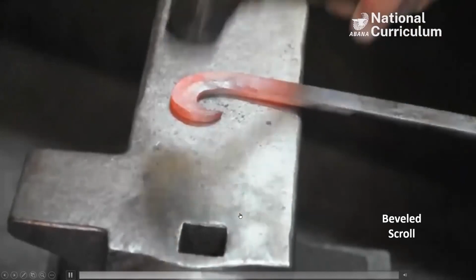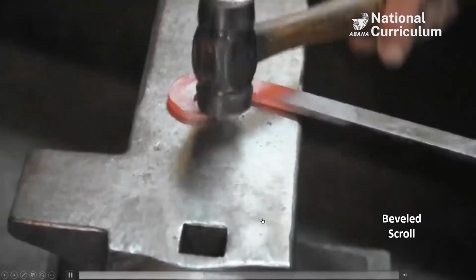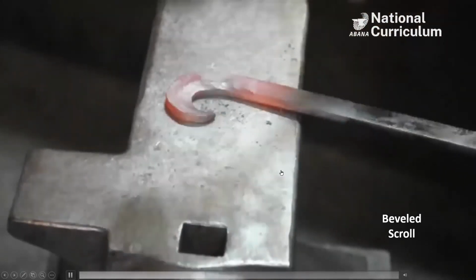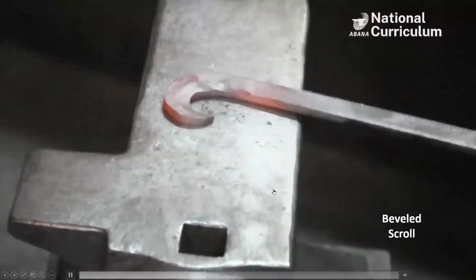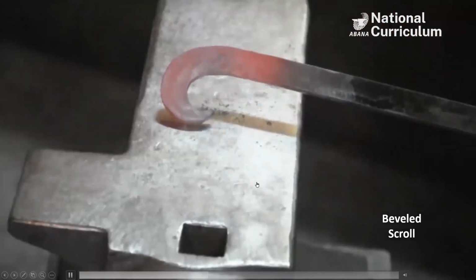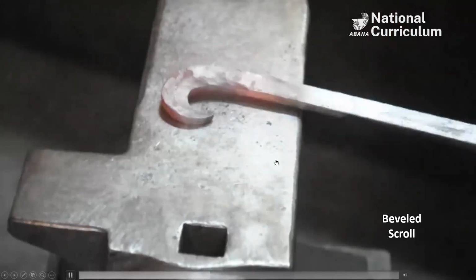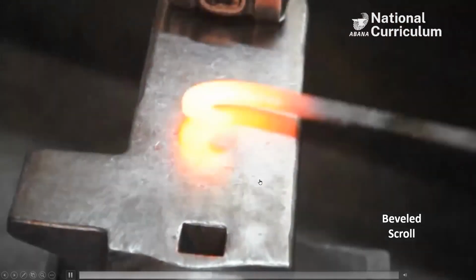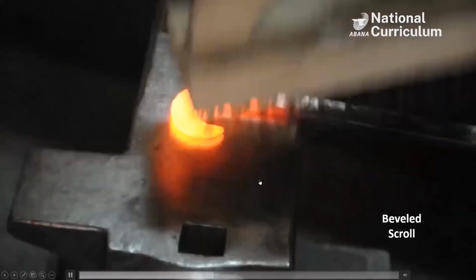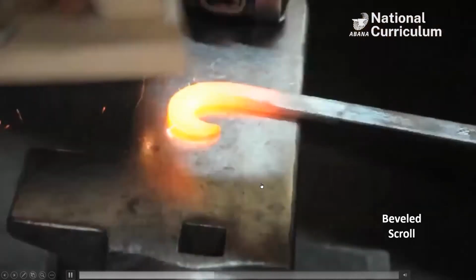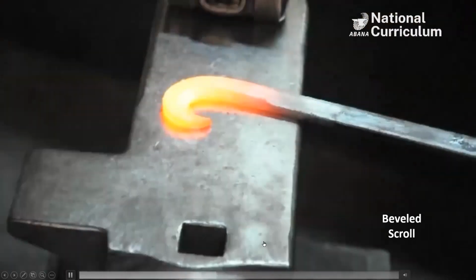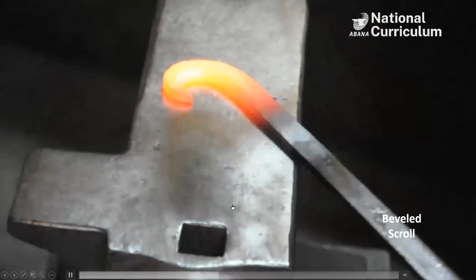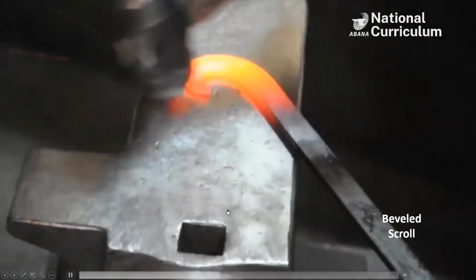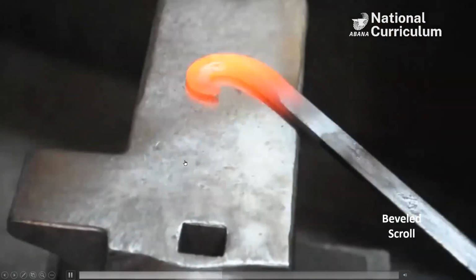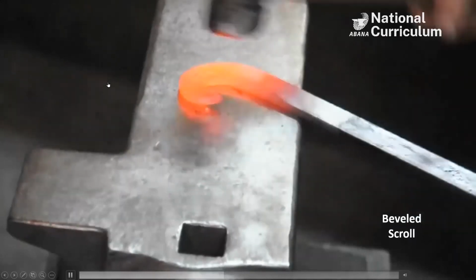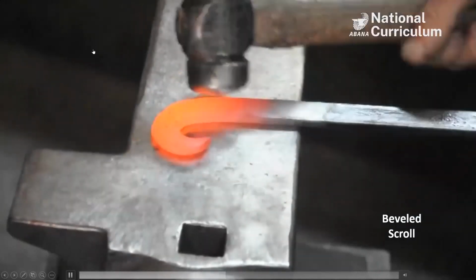And then when you come to the outside, you give that a beginning, and then you start seeing the ridge in the middle, and you can play with that and move it a little outside, little inside until it's where you want it to be. I realized that it's very easy to hammer scale into these ridges, and it doesn't look very nice. That's why I cleaned it extra nice before I started on the outside.